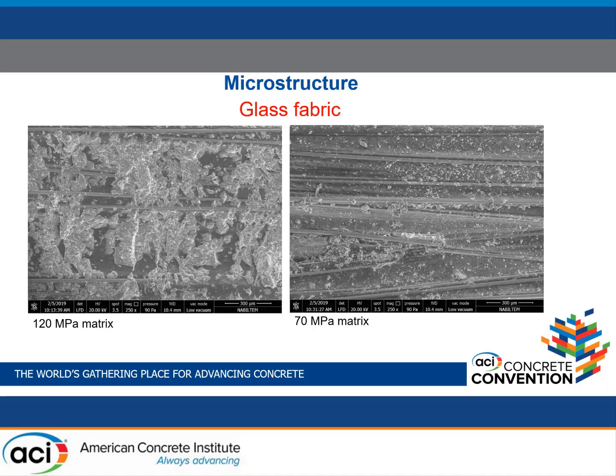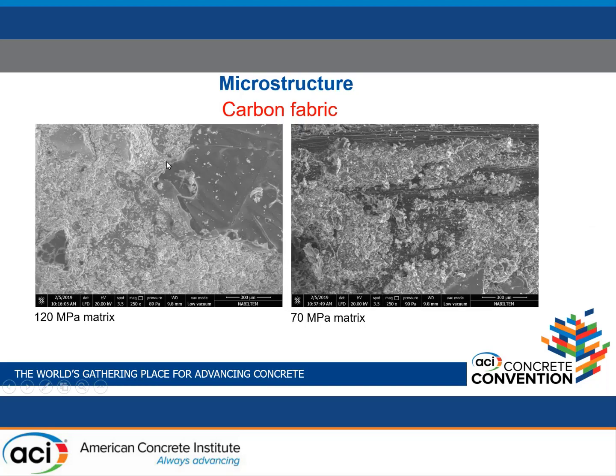glass fabric. We can conclude better bonding from the matrix residue on the fabric after failure. So you see over here that in the high strength, high performance matrix, the bonding is better. The residue of the mortar on the fabric is much higher than in the lower strength cementitious matrix sample.